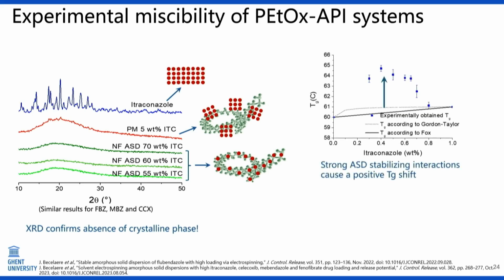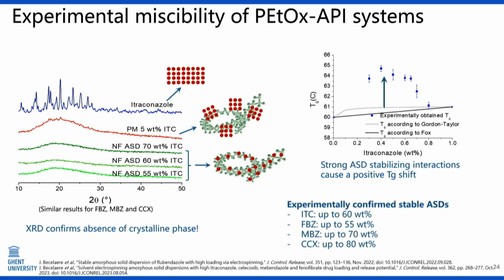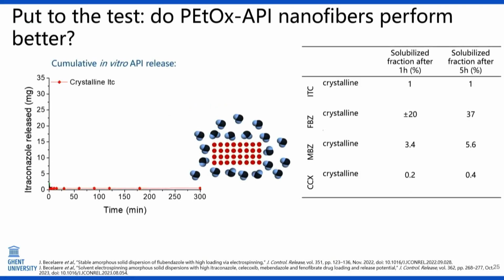We also proved that there are strong interactions. We've done this with infrared and DSC, and that these interactions are important to stabilize the drug. And then we experimentally confirmed we can indeed go to very high drug loadings for all the 4 drugs that we tested. But then, of course, we can make them, do they now solubilize? Do they give a good solubility?